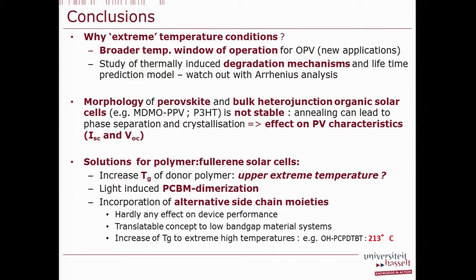We've seen also that the morphology of perovskite and bulk heterojunction solar cells is not stable as a function of temperature, and that the temperature affects the PV characteristics and the current and the VOC. For the polymer fullerene solar cells within the Institute, several routes have been proposed to improve this stability. We've seen that increase of TG can be very successful. Could also be that this TG determines your upper temperature for your operation window. If you say, organic based solar cells, which temperature window can you use it? Could be that the TG is the upper limit.